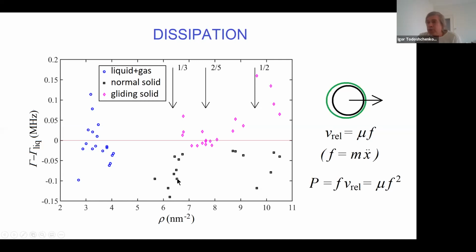Squares correspond to the normal solid. And as one would expect, the normal solid is more stiff and the dissipation is smallest. Here is dissipation in the low temperature phase minus dissipation in the liquid for easier comparison. We see that all squares, all normal solid data, have a lower dissipation than the liquid. But these red diamonds are for gliding solid, and we see that it has the same dissipation as liquid, and in many cases even much stronger dissipation than the liquid. So we can say that this gliding solid is even more mobile than the liquid.